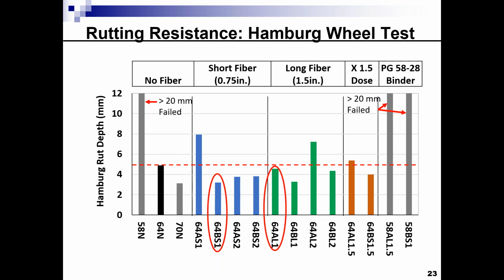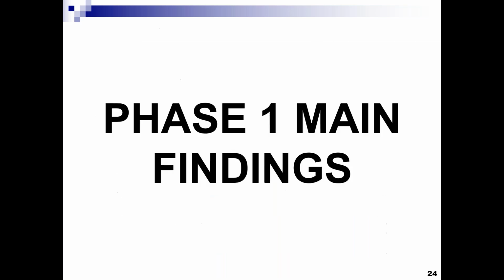If we're comparing whether we're using fiber A or fiber B, we're seeing that if we compare it to the control 64, for the fiber B, it was very similar to the polymer modified. For the fiber A, it had higher rutting as compared to the polymer modified. But the optimal that we can see is using a fiber B with a short length and a dosage that is recommended by the manufacturer, as well as using for fiber A, a long fiber, which is a 1.5 length, and the same dosage.